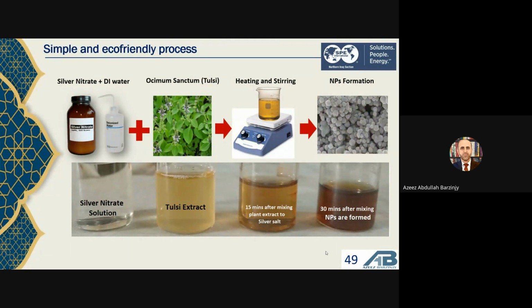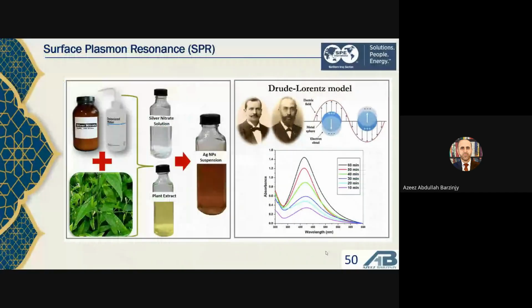So you can see at the beginning, the silver nitrate solution was colorless. Then when we add the plant extract, the color of the mixture became brownish and reddish after 30 minutes, and then the nanoparticle is formed. Then you can characterize your nanoparticle by using different characterization techniques such as SEM, EDX, XRD, and so on.